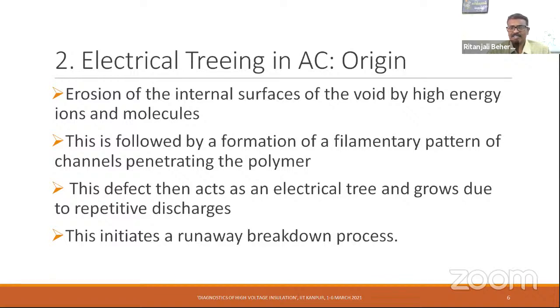This defect can act as an electrical tree and grows due to the repetitive discharges. In the tree, this leads to the breakdown process. In the treeing, an enormous amount of discharges could take place, depending upon the field condition and the nature of the material. So this intense partial discharge activity in the tree tubules would accelerate the tree channels, would increase the diameter of the tree channels, and would increase the tree structure as such. And finally, the tree structure would reach the ground electrode and would cause a catastrophic failure.